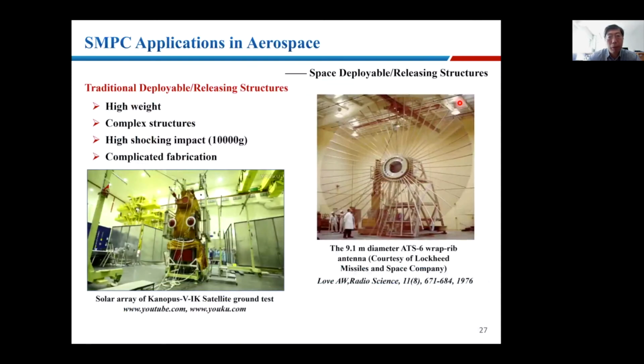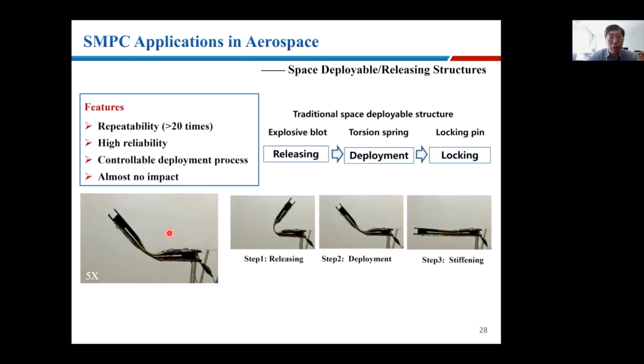So now we're talking about some applications. The first one is aerospace. You can see the traditional deployable structure is this one, with complex structures including the explosive bolt, which means a high shock impact up to 10,000 G. But with shape memory, you can easily deploy this from the initial shape. This can keep the shape at low temperature, but heating above Tg, this can deploy to the original shape. And very important, there is almost no impact. Also after you take off the heating source, the material can become very hard because the stiffness of the polymer can change. The Young's modulus can change. So this can become a load-bearing structure below the Tg.